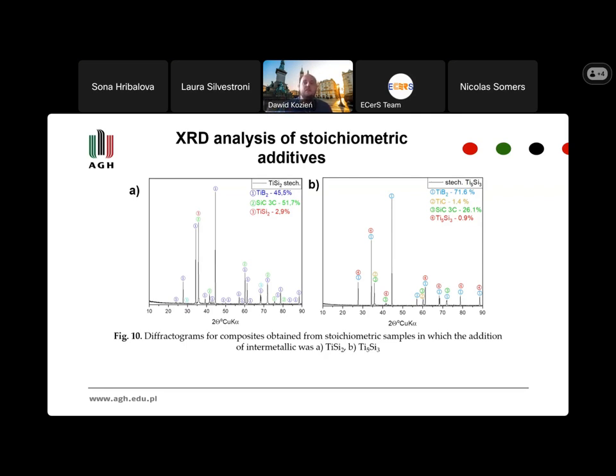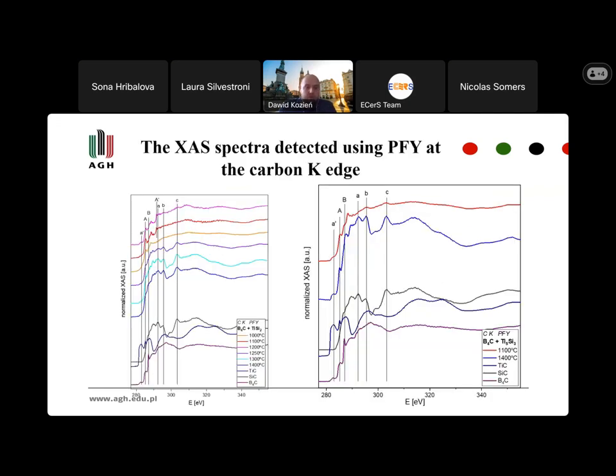And even if you want to obtain a completely new composite, we can, in the SPS method, change the temperature to 1250 Celsius degrees. So it's quite good for us to obtain something like that, because now we want to save energy and save the cost of production, and still we can lower some temperature to have better homogeneity.